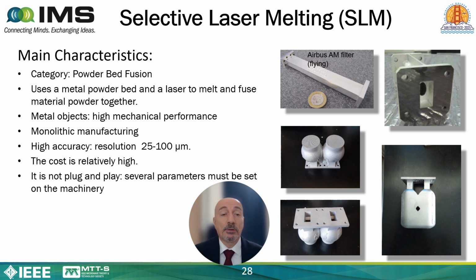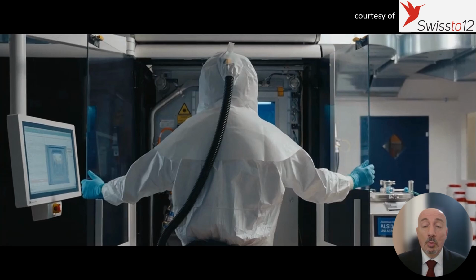Indeed, several parameters must be set on the machinery. For example, you have to select the power of the laser. If you use too high power, you risk creating a large fuse spot, and this results in poor resolution. If the power is not enough, instead, the powder particles stick to each other without fusing. This results in a fragile component and a component with higher losses. So there are a lot of things to be said, and by the way, the metal powder is also dangerous because the metal powder is very fine, and it may explode. And it is also dangerous because it can be inhaled, and it is dangerous for the health. And that's why this operator wears this strange suit in order to avoid inhaling the metal powder.